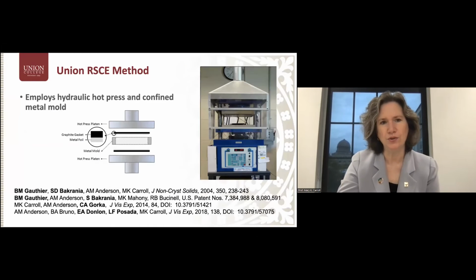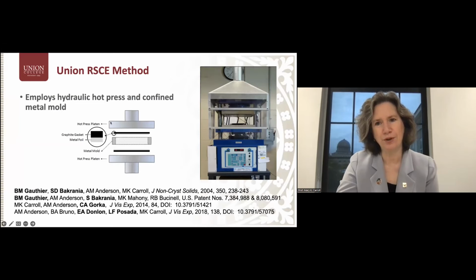The method that we use employs a hydraulic hot press. And at this point, I should say that a laboratory scale hydraulic hot press is actually considerably more expensive than a small autoclave, but we had one of them on campus. So we had access to a hydraulic hot press because it was used in a mechanical engineering laboratory.